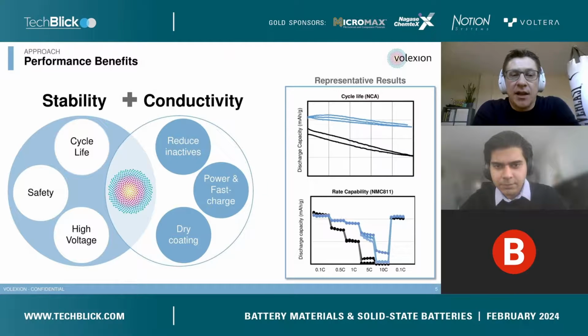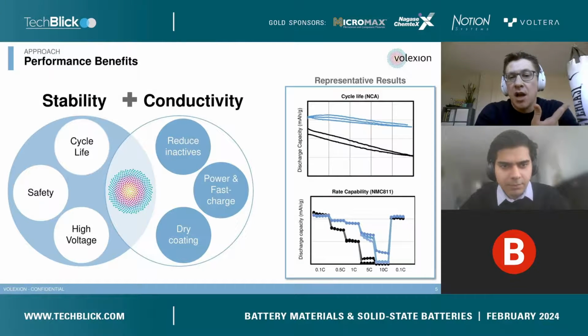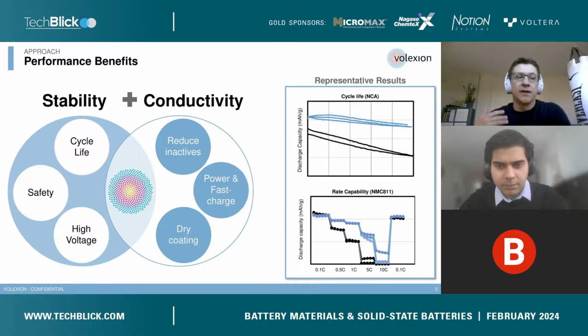On the conductivity side, we see the benefit pretty immediately by reducing inactive materials and conductive additives in the lithium-ion battery, being an enabling technology for high power density and fast charge. And finally, because our material with the coating comes pre-distributed with the conductivity benefit, it's also an enabling technology for dry manufacturing processes that are a significant topic of interest in the industry right now.